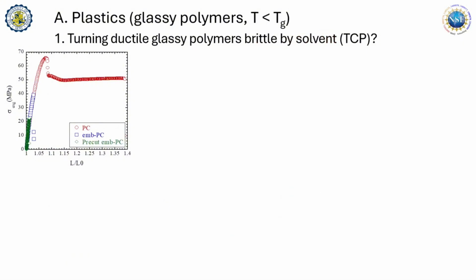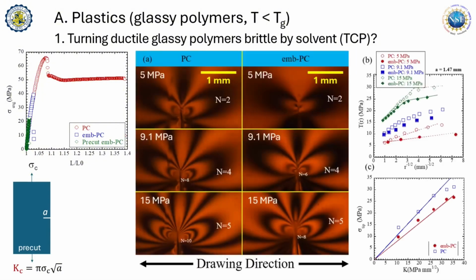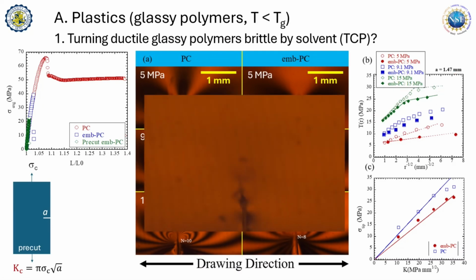So let me start, very briefly, with a case of plastics. We are polymer physicists, we can make a ductile polymer brittle by soaking in a little bit of solvent. It turns brittle. So we want a brittle case because we want to start fracture mechanics. So you do the same thing as you learn from fracture mechanics, and then you find that you can have the tip stress resolved. In other words, the tip stress does not just grow and diverge, but starts to saturate on the length scale of 50 microns, 100 microns. So I could just give you an impression of this observation.